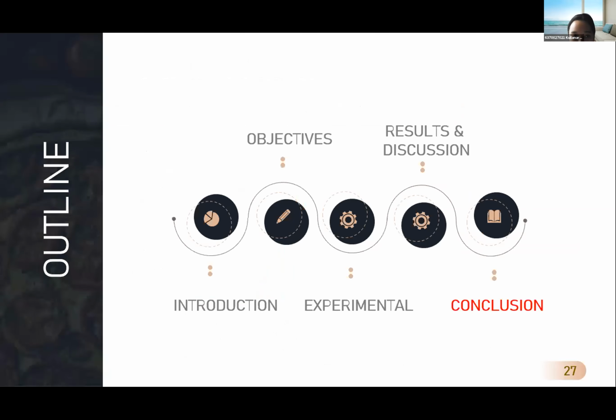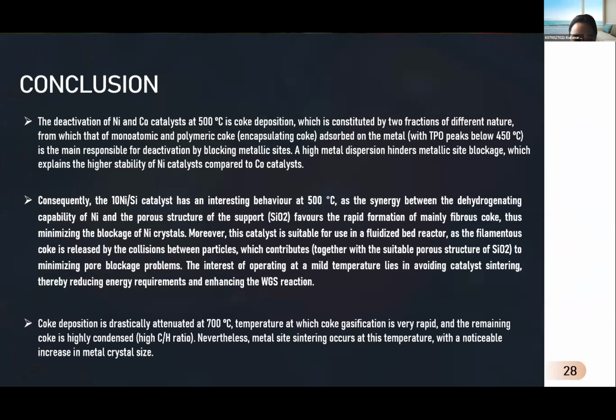In the next part, conclusion. The deactivation of nickel and cobalt catalysts at 500 degrees Celsius is by coke deposition, which is constituted by two fractions of different nature, of which the monoatomic and polymeric coke adsorbed on the metal is mainly responsible for the deactivation by coking. A high metal dispersion hinders metallic site blockage, which explains the higher stability of the nickel catalyst compared to the cobalt catalyst.